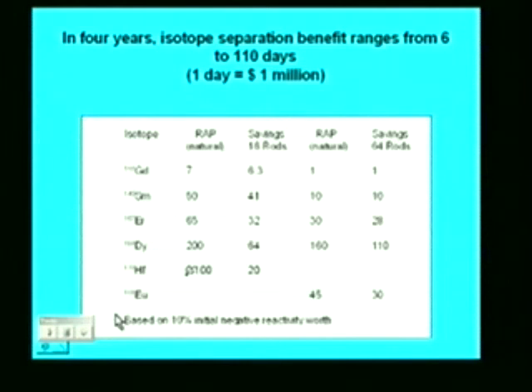Well, in 4 years, the isotope separation benefit ranges from 6 to as high as 110 days. Now, if we look at the case of gadolinium in 16 rods, that's the one where we save 6 days. In the case of samarium-149, well, you might say, well, sure, but if samarium is going to give you a penalty of 50 days, maybe you're not even going to use it. So we have to be careful how we use it and what we use it for. But if we just consider gadolinium, 1 day savings at the end of the fuel cycle is worth $1 million. So if you can run it just one more day, you've saved $1 million.